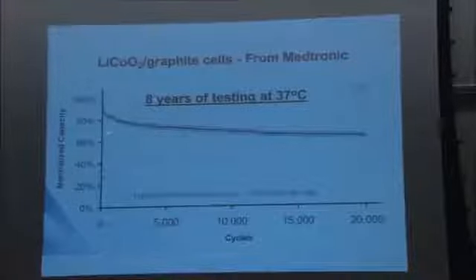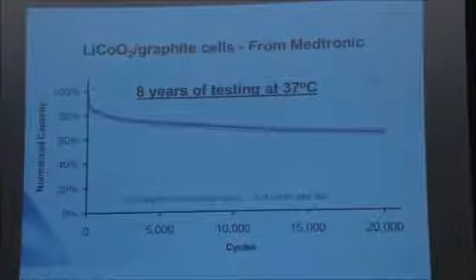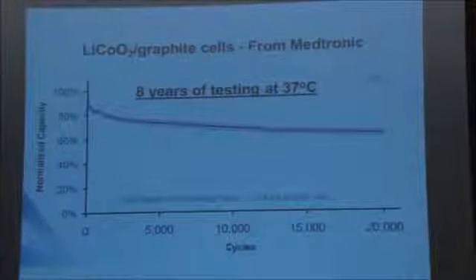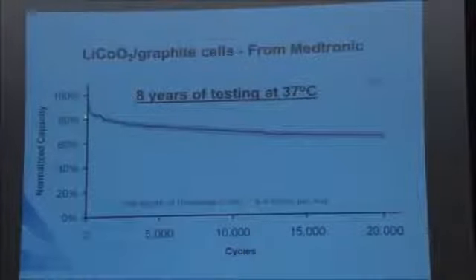Here's some data from Medtronic for cells that are implanted in the human body to run a pain relief system. They have cells in the lab that have 8 years of testing accumulated at 37 degrees C. So here you can see 6 to 8 cycles a day, 20,000 cycles, 8 years of testing at 37 degrees C. That's pretty impressive. Cells like this with nickel cobalt aluminum are in the Tesla Motors vehicle. So Tesla Motors uses technology that's at least this good. This is 8-year-old technology, right? The test started 8 years ago, so it has to be 8-year-old technology. And how do you make it better? Well, do you want to test for 8 years before you find out if it's better or not?